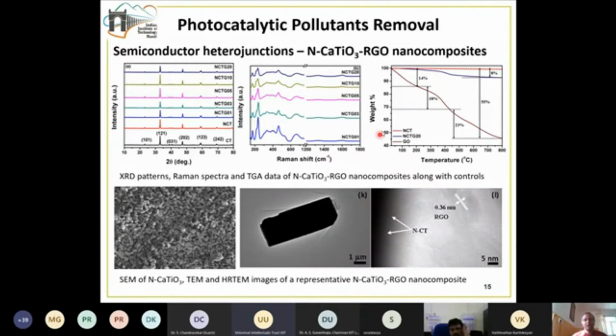Then we did the morphological studies, wherein we found that this N-doped calcium titanate has a brick type of structure. You can see small brick-shaped structures, and these bricks are sitting onto the bigger reduced graphene oxide. It's like a big carpet, and you are putting too many bricks onto this carpet. So that type of structure happens. This is the HR-TEM image.